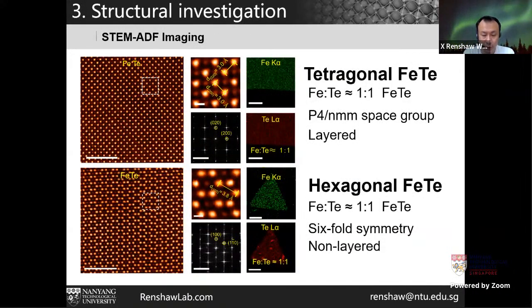Right? So that means we are successfully getting a high quality FeTe. And then we also measure the microscopic, the atomic structures. We use the TEM. So we captured the structure of the tetragonal phase and the hexagonal phase. As you can see from the high resolution TEM, we literally get atomic scale high quality, and the hexagonal phase and the tetragonal phase are clearly visible.